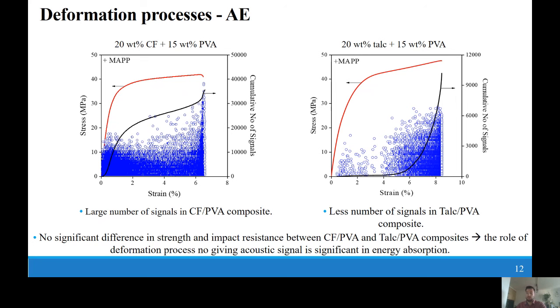In the case of carbon fiber PVA hybrid composites, two different processes can be defined. At small deformations, the fracture and the pull out of the fibers can be observed, while before the failure, the fracture of fibers is the dominant deformation process. In the case of talc PVA hybrids, no signals were detected at small deformations. Before the failure, similarly to the carbon fiber composites, the fracture of the PVA fibers gives signals.